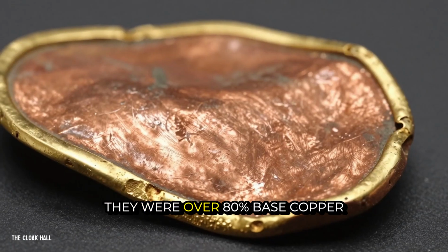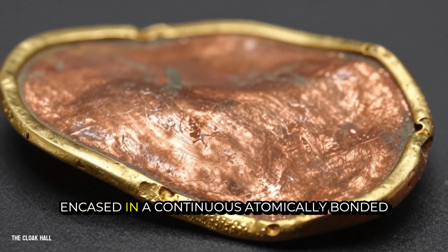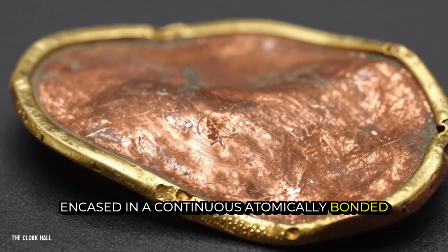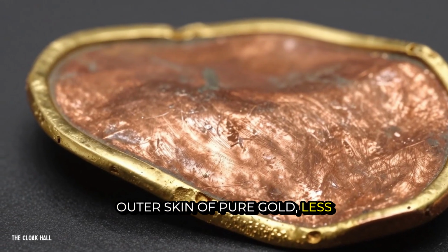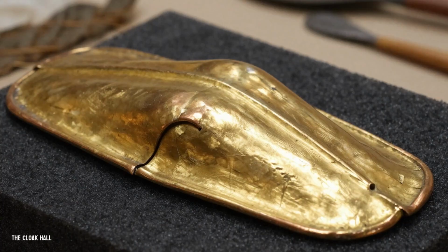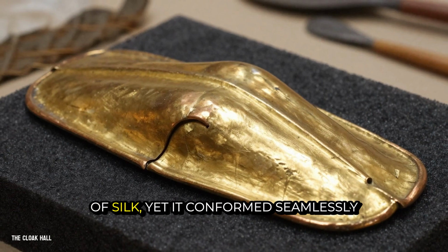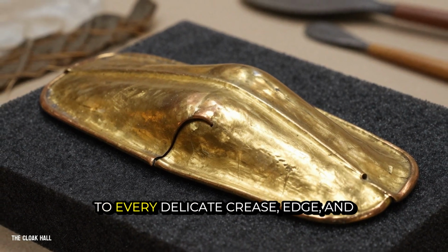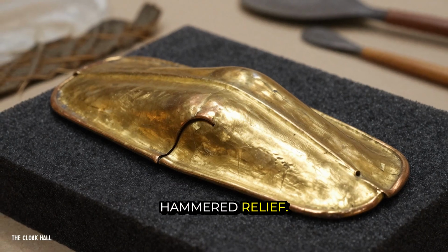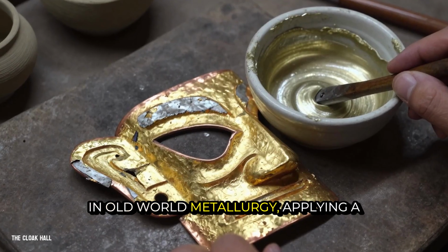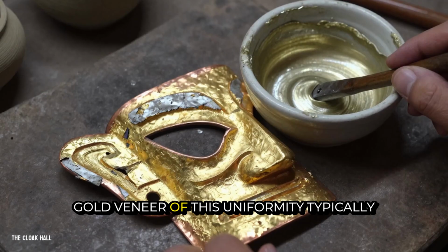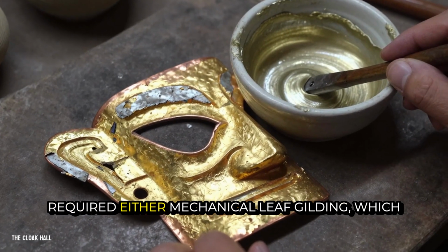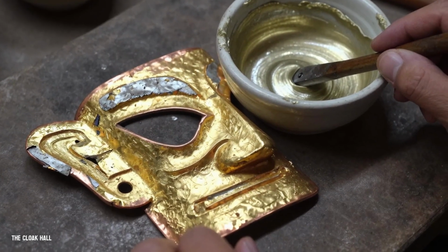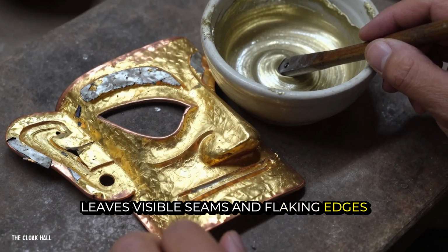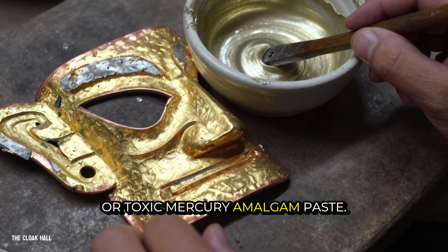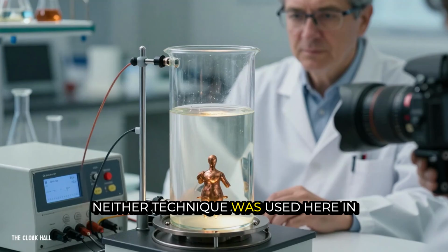They were over 80% base copper, encased in a continuous, atomically bonded outer skin of pure gold, less than a single micron thick. It was thinner than a strand of silk, yet it conformed seamlessly to every delicate crease, edge, and hammered relief. In old-world metallurgy, applying a gold veneer of this uniformity typically required either mechanical leaf gilding, which leaves visible seams and flaking edges, or toxic mercury amalgam paste. Neither technique was used here.